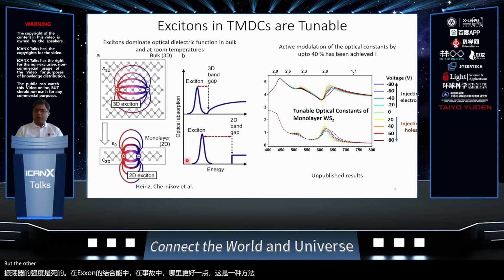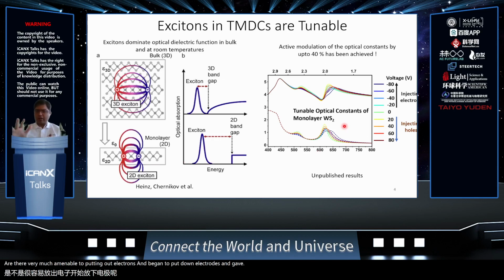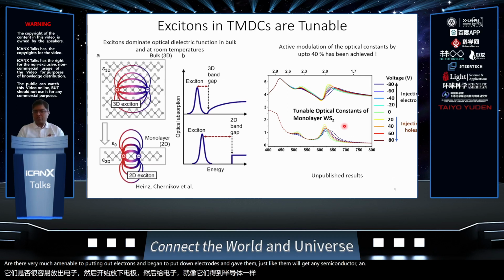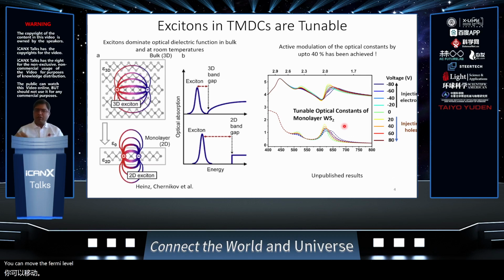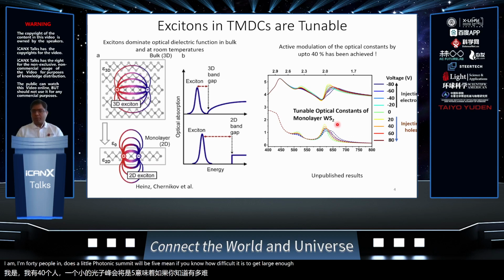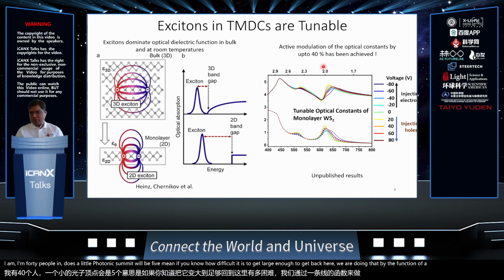But the other way to tune them, in the case of monolayers in particular, is that they are very much amenable to putting down electrodes. And once you put down electrodes and gate them just like you would gate any semiconductor in a transistor, you can move the Fermi level, and then you can change the optical constants by a very large magnitude, right? I'm sure the people in the silicon photonics and other III-V communities know how difficult it is to get large electro-optic effects. Here we are showing that as a function of applying voltage or electric field, you can tune the indices by up to 40%.